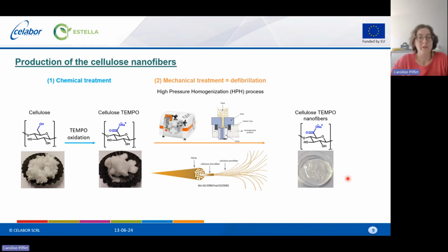And so first, at CELABOR, we produced the cellulose nanofibers. So I will explain how we proceed. We have our cellulose, which is a polymer that can react chemically. And we performed an oxidation with TEMPO reactant. This oxidation allowed us to graft a carboxylate group on the polymer chains. So we obtained this kind of compound.